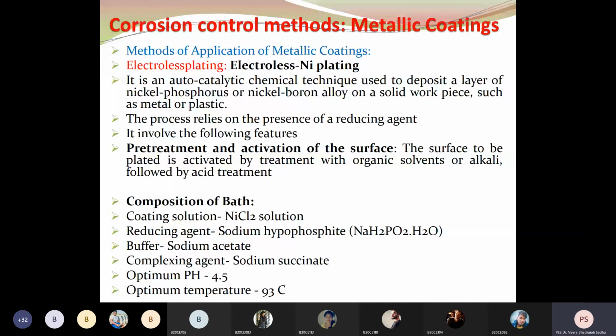So what is in the bath? It contains the coating solution of nickel chloride, and a reducing agent, which is sodium hypophosphite, and a buffer, which is sodium acetate, and sodium succinate is the complexing agent. The optimum pH for this nickel plating is 4.5, and the optimum temperature is 93 degrees centigrade, because these are the optimum conditions to get a proper nickel film. Some scientists might have worked at different conditions, but this is the optimized condition where you get better values.